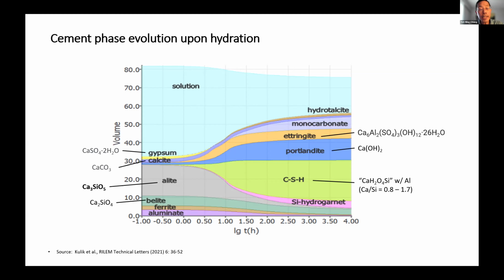What you see is that as the alite phase, that gray band disappears, the predominant new phase that appears is calcium silicate hydrate, or CSH. Okay. This is the binder phase in cement that is the glue that holds everything together. And what you see is that there's actually an excess of calcium hydroxide produced in this process. But most of the calcium is used to produce the CSH.